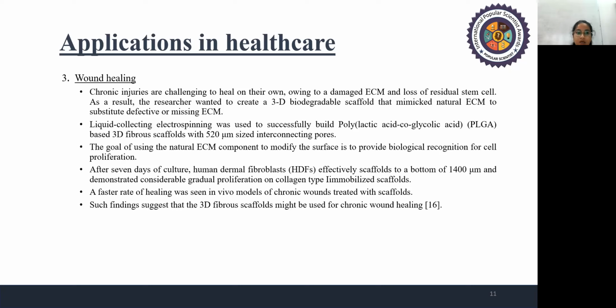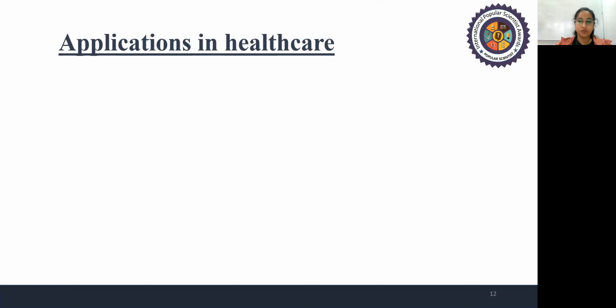So there is a study where liquid collecting electrospinning was used to successfully build a poly(lactic-co-glycolic acid), PLGA, based 3D fibrous scaffold with 520 micrometer sized interconnected pores. The goal of using natural ECM components to modify the surface is to provide biological recognition for cell proliferation. After 7 days of culture, human dermal fibroblasts effectively infiltrated the scaffold to a depth of 1400 micrometers and demonstrated considerable gradual proliferation on the collagen type I immobilized scaffold. Such findings suggest that the 3D fibrous scaffold might be used for chronic wound healing.